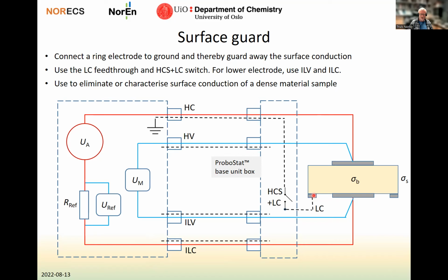You connect this now to the shield system, and you connect the low current electrode to the surface guard electrode. And then for the lower electrode to the sample, you use the inner low voltage and inner low current, which are still available from the inside. Now, any current that goes on the surface will be led to ground, and therefore it does not count in the measurement. So you only measure what goes through the sample. This is used to eliminate or characterize surface conduction on a dense material sample.